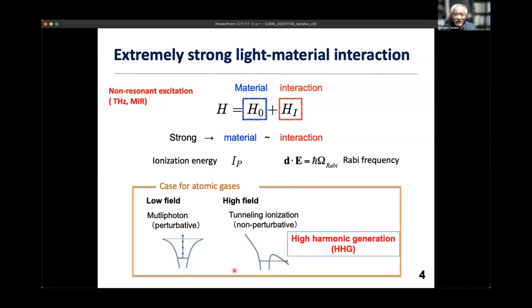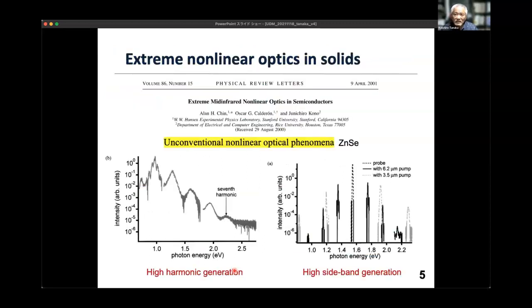But in solids, people also try to see this extremely nonlinear effect. Maybe the first report appeared in 2001 from the Rice University group, Professor Kono's group. They showed unconventional nonlinear optical phenomena in several semiconductors. Here I show you two results in zinc selenide. This one is high harmonic generation. They used a mid-infrared laser around 3 to 4 micron, and obtained this very nice 7th harmonic here.